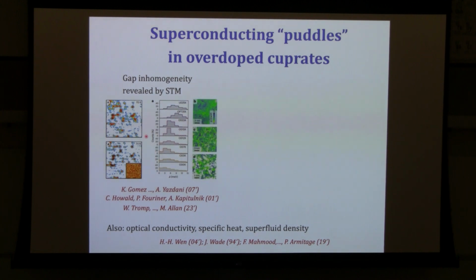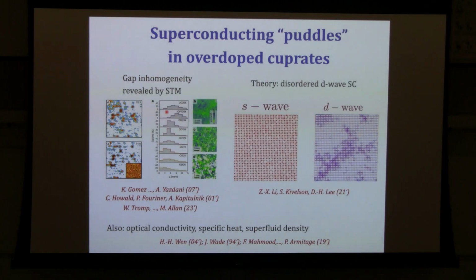Okay, so what's actually causing this type of behavior, this sort of inhomogeneous suppression of superconductivity? We think we have some understanding thanks to work done by Steve. This has to do with the way that superconductors react to disorder. A conventional S-wave superconductor is relatively insensitive to disorder, but an unconventional superconductor like these cuprate materials, a D-wave superconductor, is actually extremely sensitive to disorder. And that means that when you add disorder, it would be destroyed eventually.